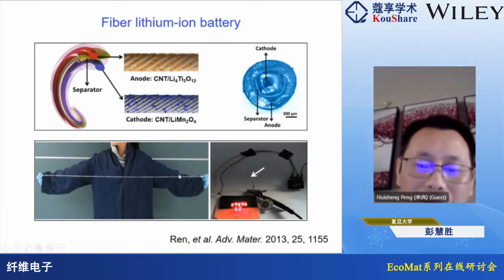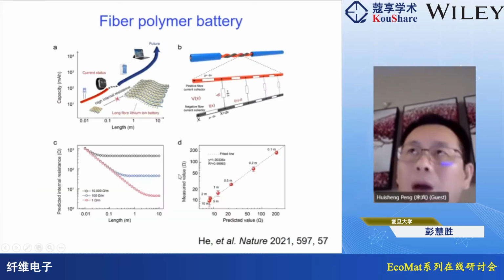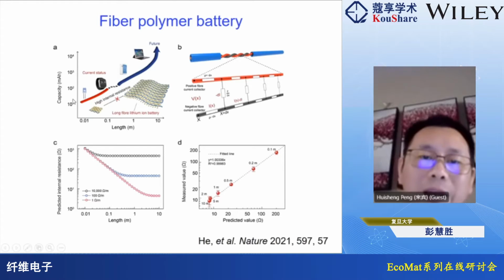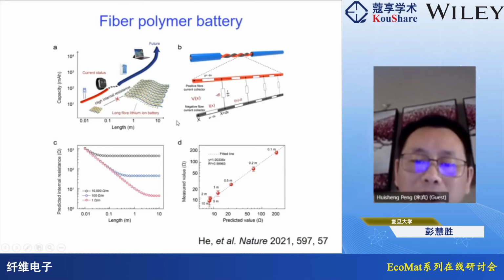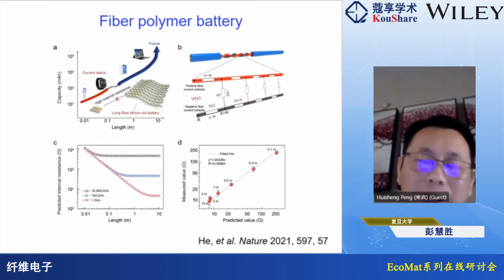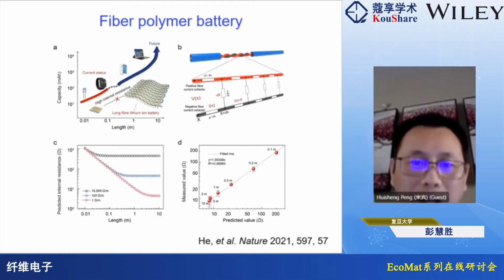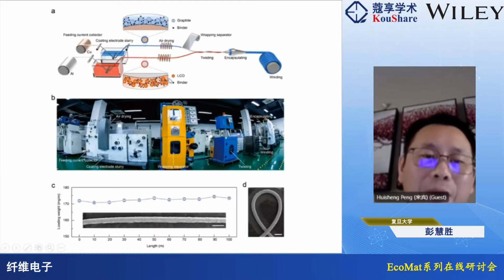We got the first fiber batteries in 2013, and they could be continuous, but the properties were very poor. So then we tried to optimize the interface and the materials, and especially used fiber electrodes with much higher conductivities. And then we can get much higher performance fiber batteries. We can even make them with a continuous facility. We can scale up now.